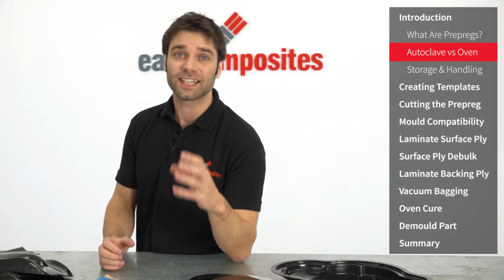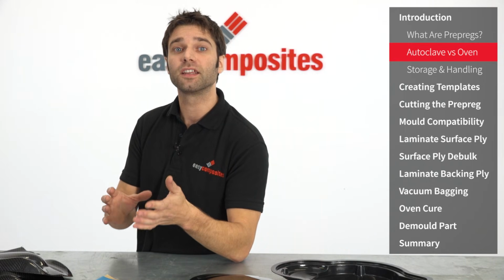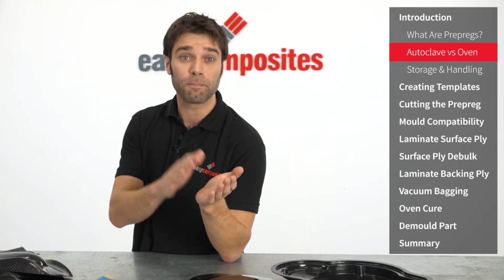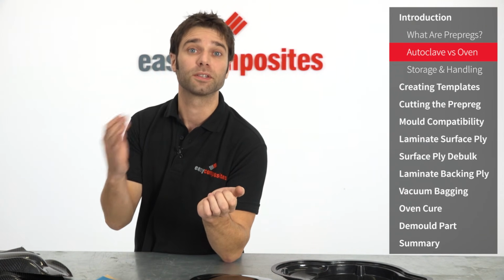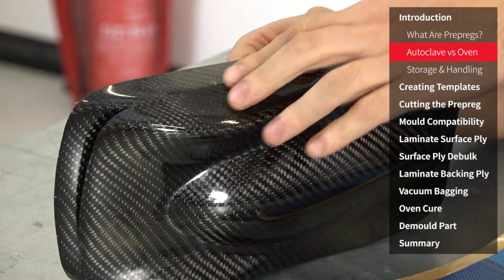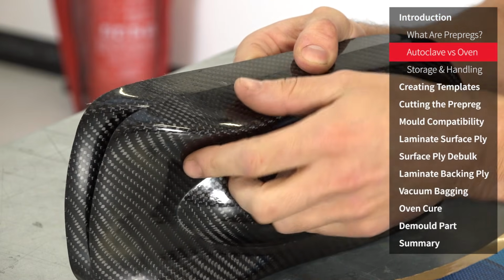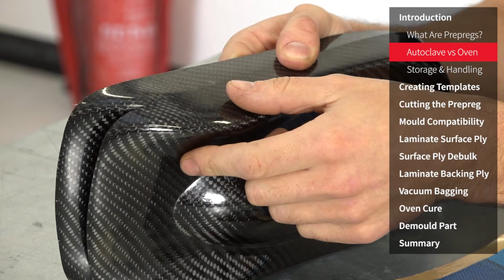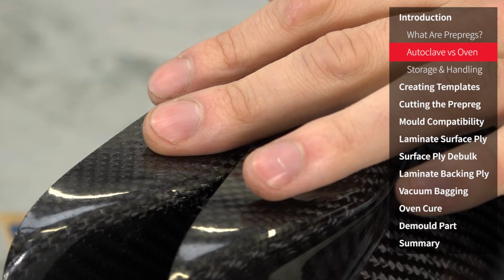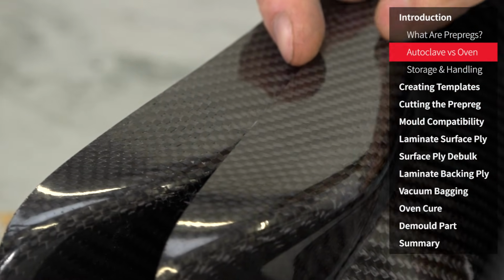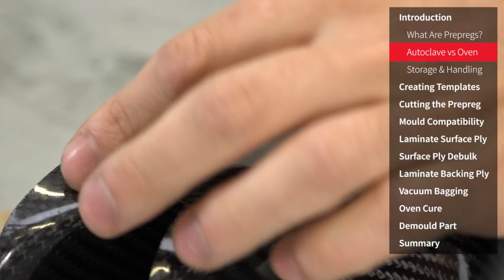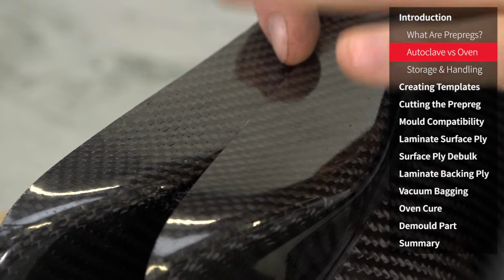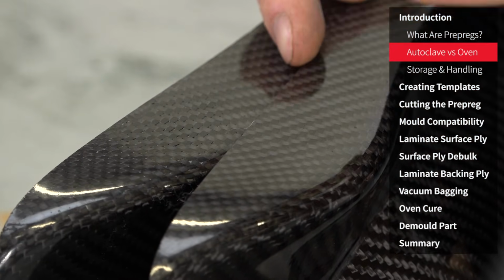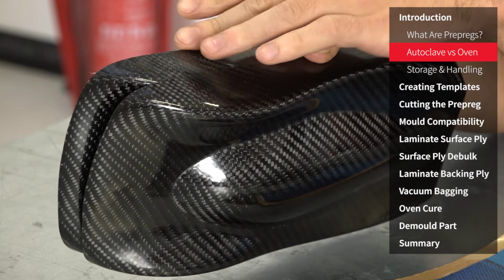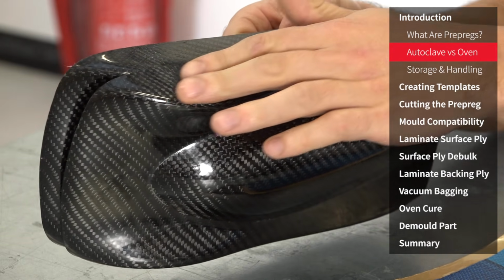However, the XPREG XC110 system has been painstakingly developed to deliver results that are comparable to the results that you would get when processing with an autoclave. I've got a couple of examples here which clearly illustrate the difference between the XPREG XC110 and a conventional pre-preg. You'll notice that the 110 is void-free, whereas the conventional pre-preg here has surface imperfections all over. And this is typical of any attempt to process a conventional autoclave pre-preg in an oven.